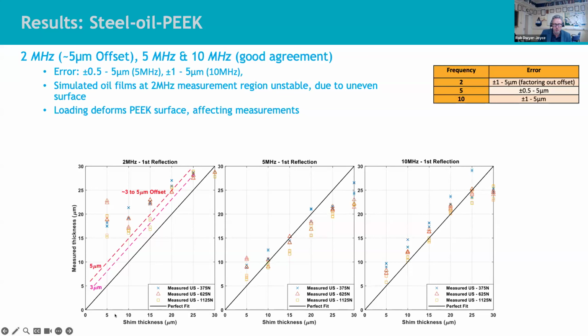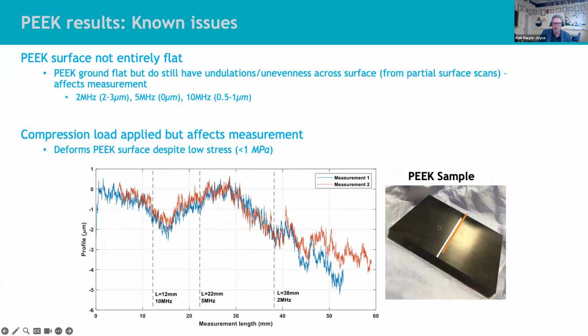We did many more different shim thicknesses as well. They tend to work a bit better at higher frequencies, in fact. One of the problems is generating the oil film. First of all, our PEEK surfaces weren't particularly flat. Here's our measurement of our PEEK surfaces, and you can see that it's quite a way off flat. When it's 2 microns off flat, and you're only trying to measure 5 microns, this is a significant error in the measurement. We have tried grinding this, but really can't get it much better.